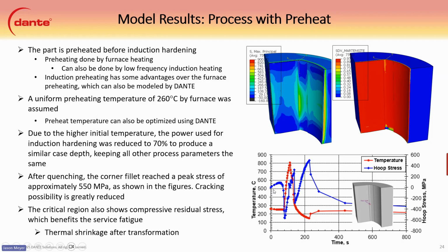And you can see the same kind of stress reversals here. We go into compression here from the heating. We go into a little bit of tension from the continuing heating and the balancing of the material around it forming. And then we have the transformation of martensite, which brings it back into compression. And then it does go back into a little bit of tension, like I said, about the 550 MPa, before actually cooling down completely and going back into compression overall.